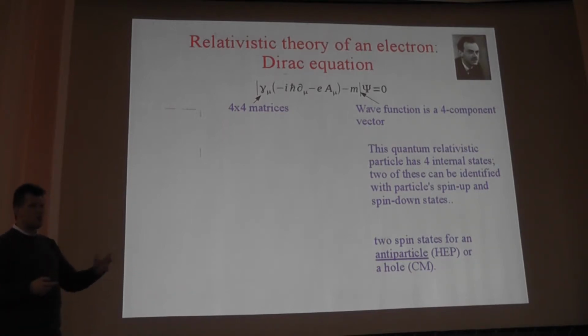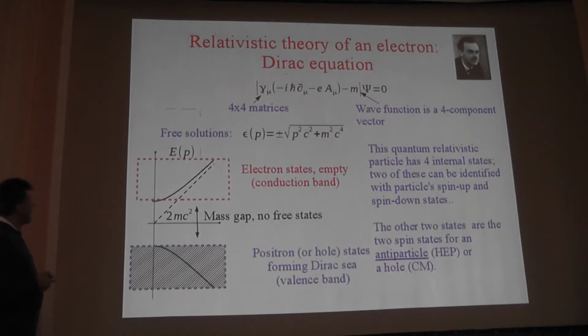You can identify a twofold degeneracy with spin up and spin down, if you recall that the electron is a spin 1/2 particle. What's the origin of the other two states? Well, the origin is that if you actually solve for the dispersion, you'll find out the relativistic root has a plus-minus sign. So the full dispersion described by this equation has 2 bands: positive dispersion, negative dispersion. In general, there is a nice gap between the two. These are electron states, and these states are either called positron states if you are a high energy physicist, or hole states, or valence band if you are a condensed matter physicist.